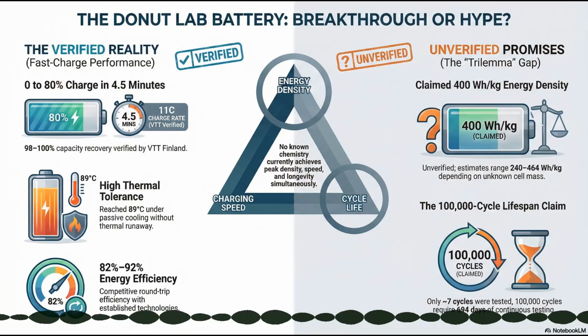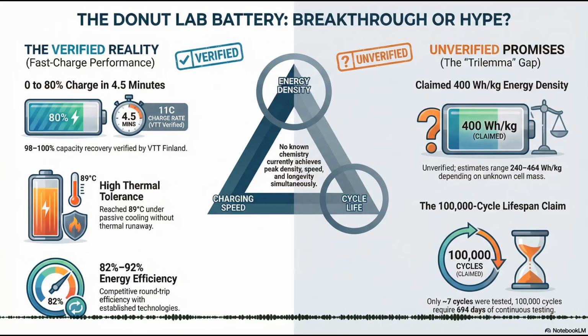This is the single most important data point in the first section. After these massive high-rate charge events, the capacity recovery remained between 98.4% and 99.6%. So it actually held the energy. It proves the cell isn't just taking the current and dissipating it as heat, or worse, plating metallic lithium on the anode surface. Let's talk about the plating for a second, because at 286 amps, lithium plating is usually guaranteed.